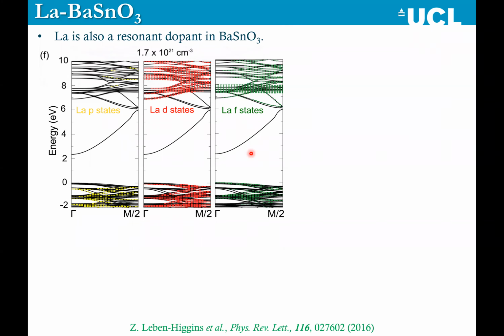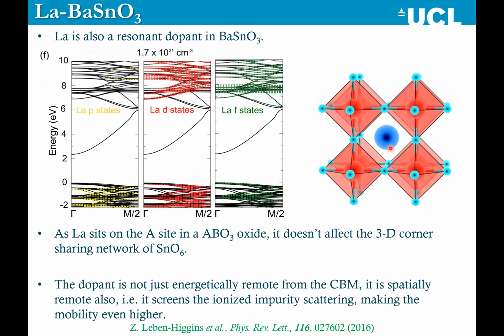So you have that energetic separation between the conduction minimum and the lowest lanthanum states. But you also have the spatial separation, because the lanthanum is on the barium site, which sits in this hole between these octahedra, whereas the tin oxygen network is the 3D corner sharing network through which the electrons move. So you don't just have an energetic separation, you actually have a spatial separation between the scattering ion and the electrons that are zipping around in your material. And what this gives you is it screens the ionized impurity scattering, making the mobility even higher.